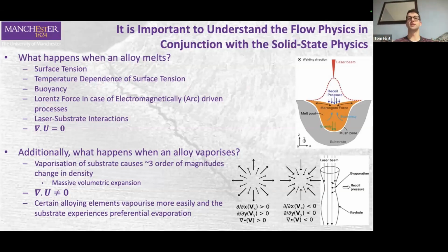They're like surface forces, and Marangoni force is normally one of the dominant forces, and that arises because the surface tension of liquid metals is actually quite strongly dependent on temperature. So when you have a higher temperature in the middle of a weld pool, for example, you will get tangential flow across the surface of the weld pool because the surface tension is essentially lower in the middle of the hot region compared to the outer region. That's called Marangoni flow. If you drink wine, you get the same effects due to concentration in wine. People call it the tears of wine, I think. So basically, we've been developing these frameworks that describe this process.